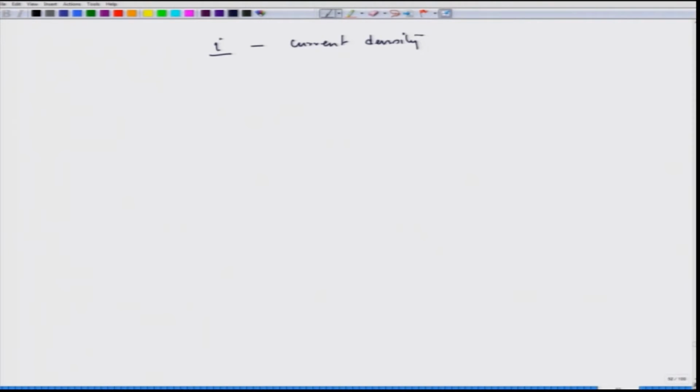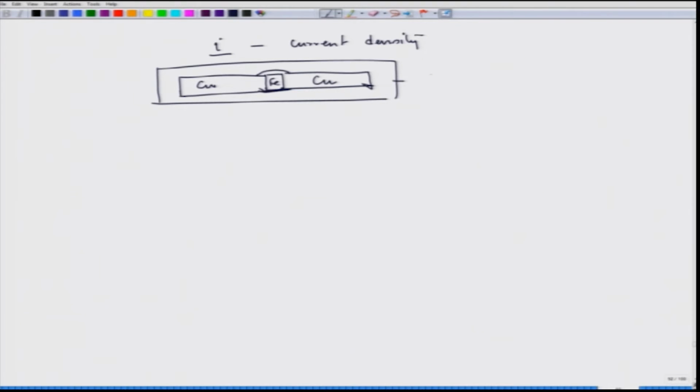If we recall, we saw that in the case of galvanic corrosion, if we have a copper plate, another copper plate, and an iron rivet connecting these two copper plates, and we put it in NaCl solution, then according to galvanic corrosion, the iron will dissolve quickly and finally the rivet would lose its joint strength.